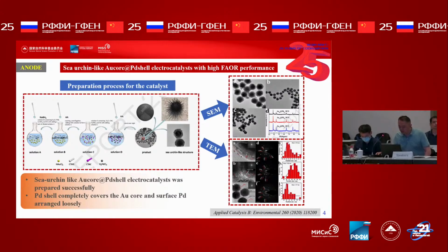Here, I will start with interesting work in which we developed a uniform sea urchin-like gold core and palladium shell electrocatalyst for formic acid anode oxidation. As seen in the TEM, the gold core is successfully covered by the palladium shell, with the particles homogeneously dispersed, like this.